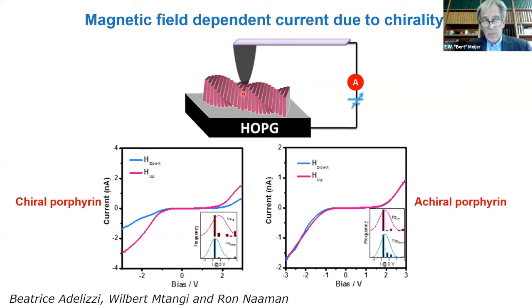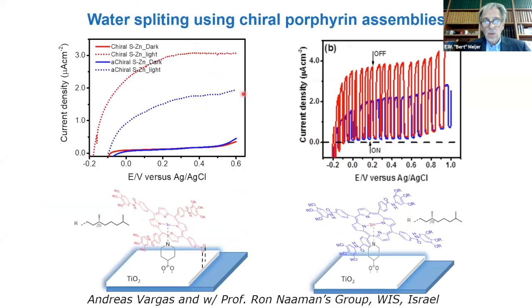Now, I was happy with it, but I was not very convinced because the effects are small and I didn't know exactly how that tunneling would go. So we started to work on water splitting. And although we're still not completely sure how it all goes, the most remarkable part is that we always get more hydrogen produced, and we also get more current when we use the chiral structures on the surface instead of having an achiral structure. So that looks like that spin effect really works.